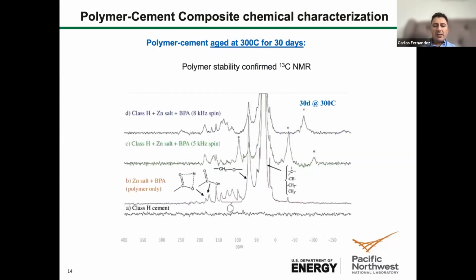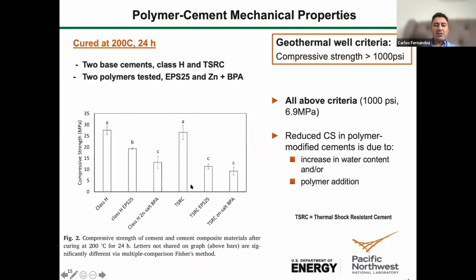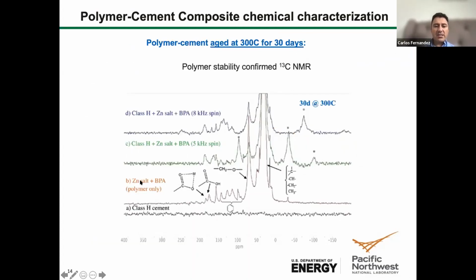And this is also for cement H. We don't have any NMR for TSRC, but at 300 Celsius for the zinc salt BPA cement, 30 days at 300 Celsius, the structure of the polymer is still intact and interacting, as you can see here, with the calcium of the cement. And this is the carboxylic acid of the polyacrylic acid zinc salt. So the carboxylate is a salt, and it exchanged the zinc of the salt with the calcium of the cement. And that could be one of the mechanisms, the reversible interaction between the calcium and the carboxylate, one of the mechanisms for self-healing.